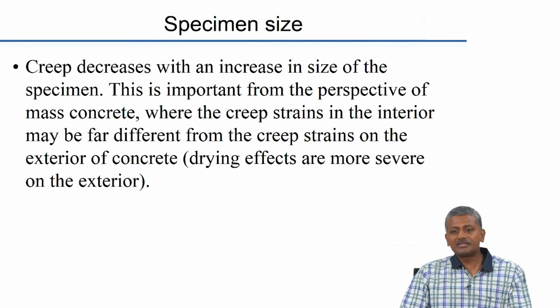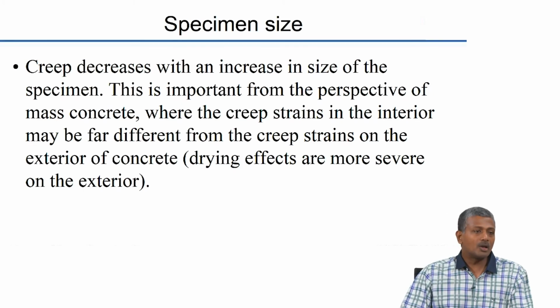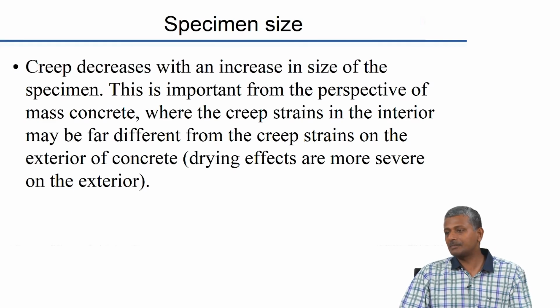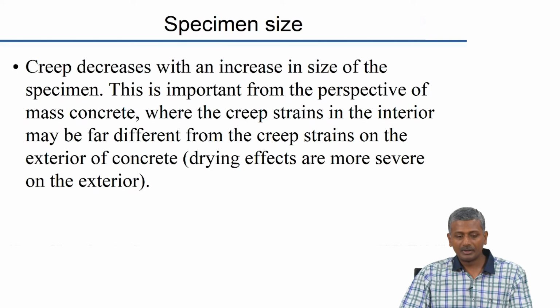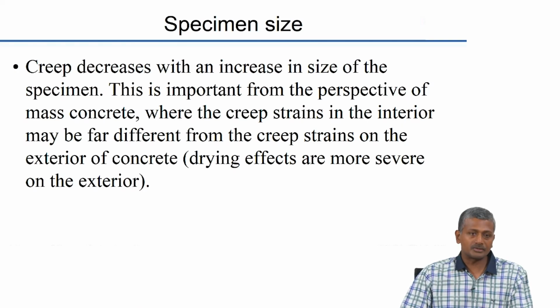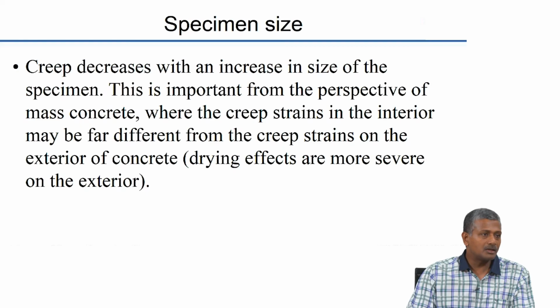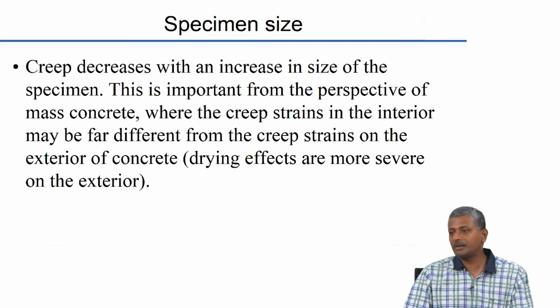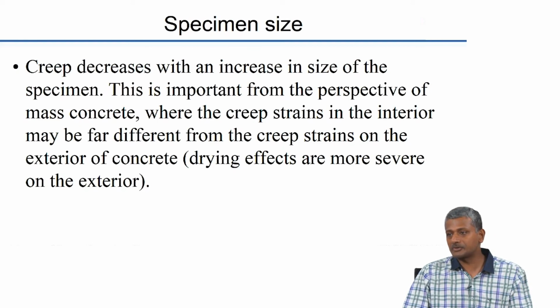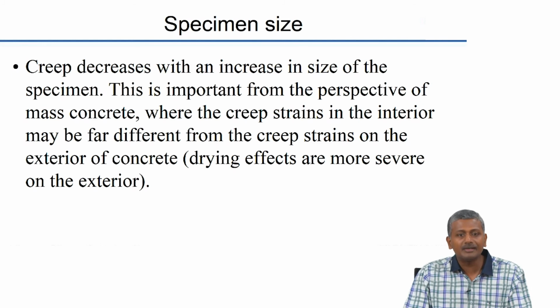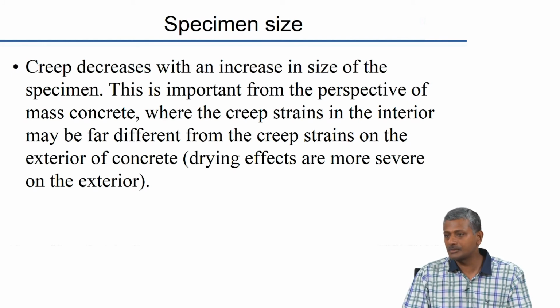Now, you can rightly imagine that when you are going from small to large specimens, the effect of creep could be quite different. As the size increases, you have lesser and lesser creep that actually happens in the system. Okay. So, again this could have different connotations. When you have very large specimens, the creep which is in the interior of the specimen could be quite different from the creep strain at the exterior of the specimen. So, you create what is known as a strain gradient, and that can lead to cracking in your system.